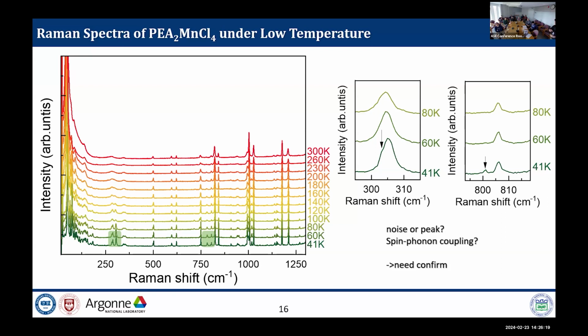Near the 305 inverse centimeter peak, this one, there seems to be some peak splitting. Above the Néel temperature, the octahedra vibration mode is degenerate and there is just one peak. But below the Néel temperature, some magnetic ordering, the manganese-chlorine-manganese chain, some super-exchange interaction, breaks the degenerate state and splits it into two different peaks. So this is why the peak splits near 305 per centimeter.